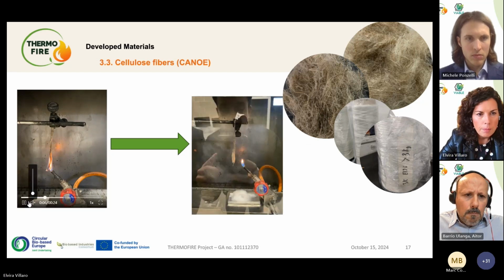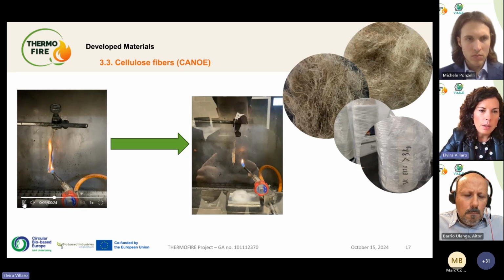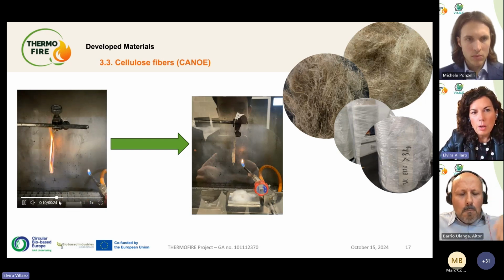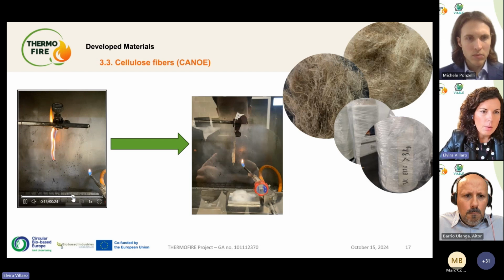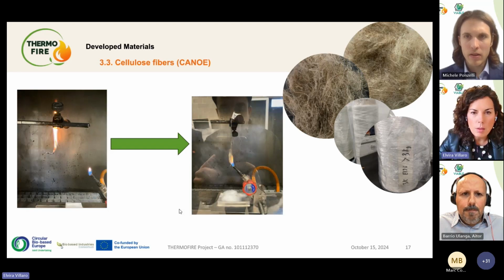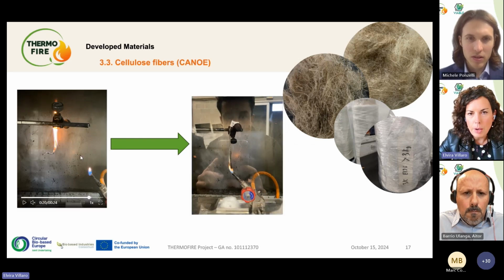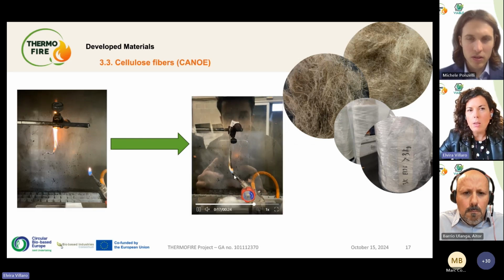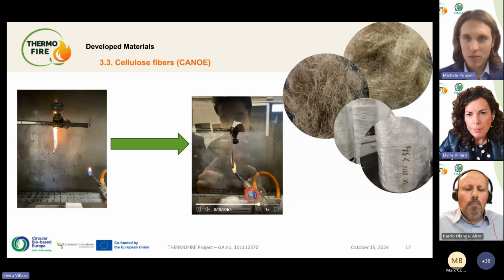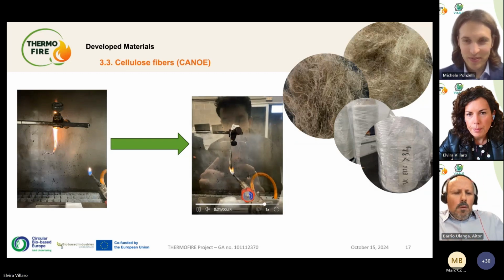So it's really slow. But at the end, you can see that after 10 seconds of flame exposure, in the case of the treated fiber, this is not burning. This is self-extinguished by itself. If we compare the non-treated one with the treated one, you can see that the flame is not spreading and it's self-extinguished, but it's really slow. Yes, we can appreciate this.